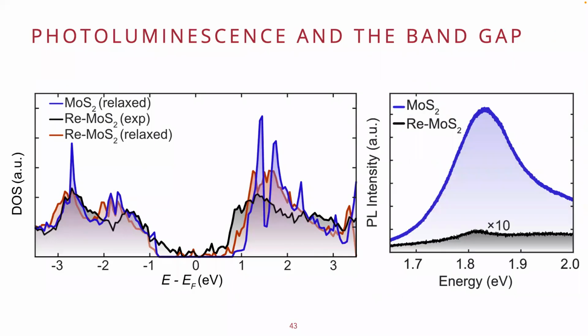We performed photoluminescence spectroscopy to see if this matched with reality, and we saw that it basically did, right? In moly disulfide, we would expect a nice peak from our exciton energy. No matter which area we tried, it was a little bit variable, as you would expect, because the distribution of rhenium atoms is not uniform. This is the best case area that we could find of any signature of an exciton, and this is blown up by an order of magnitude, right?